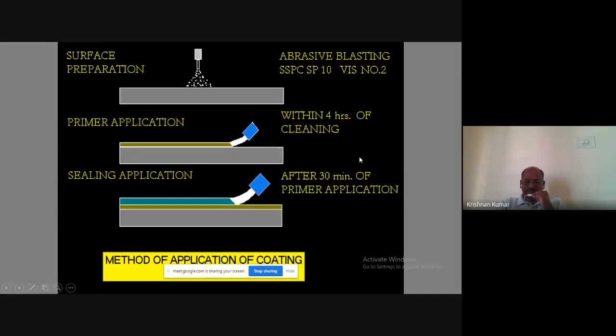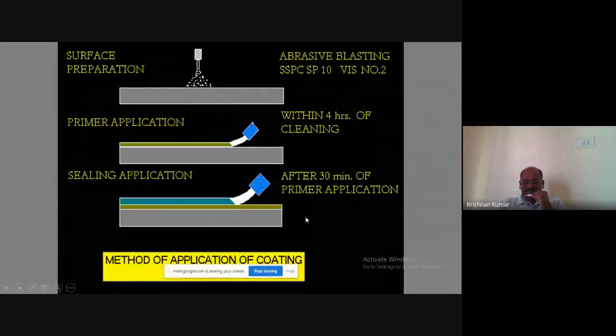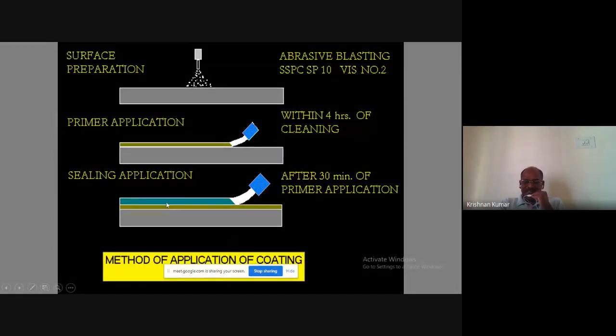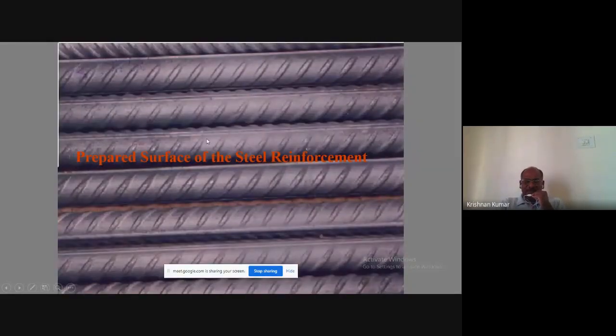Now this is the process. How to make it: the surface is to be clean, by any kind of abrasive blasting. Don't use acid cleaning. After the surface preparation, within 4 hours, the primer coating is to be applied. The primer coat is of fast curing type. Within 30 minutes, you can go for the sealing coat. When this is over, within 6 hours the coating is ready to be handled, because it is such a fast drying coating system. So people can use it for construction immediately. This photograph shows the prepared surface of the steel reinforcement.